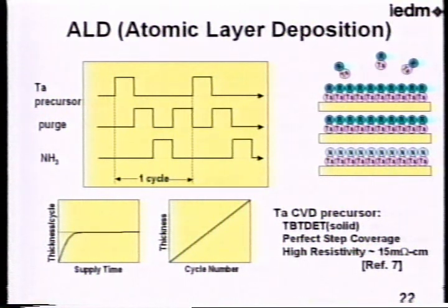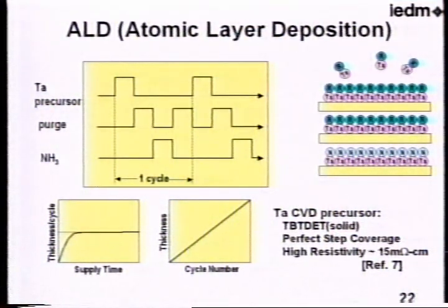ALD is a very promising candidate for conformal and thin film formation. In an ALD process, gases are introduced cycle by cycle. The precursor gas is adsorbed initially at the surface of the substrate, followed by a surface reaction to form an atomic layer of metal. In that case, the step coverage is perfect. But the problem with ALD is that it's somewhat difficult to find a suitable precursor, especially for tantalum. Of course, there are some reports on tantalum CVD precursors. It will give a perfect step coverage, but the resistivity is very high at this moment.